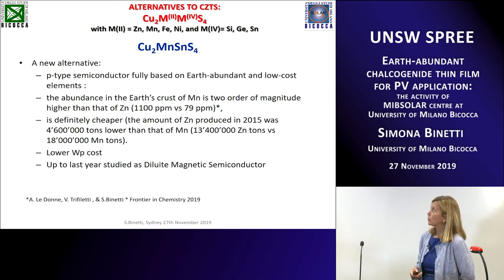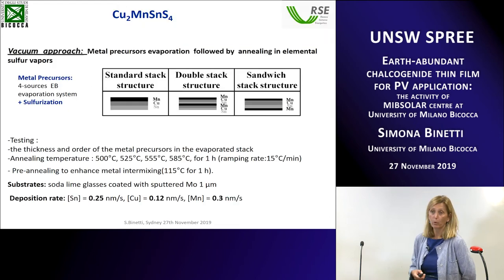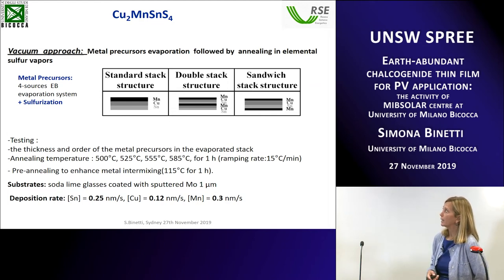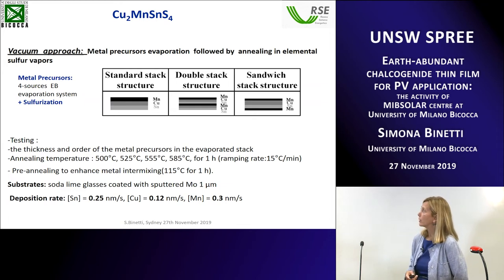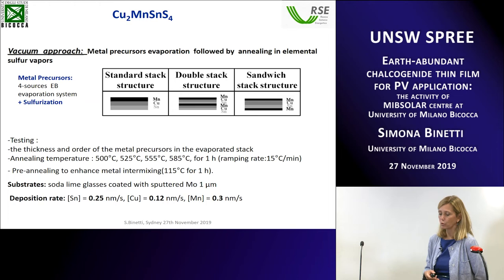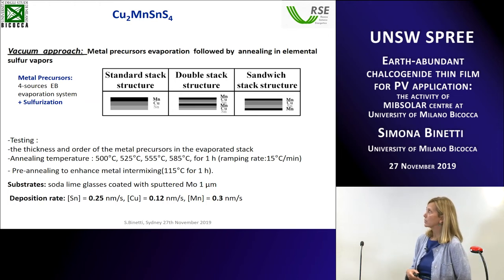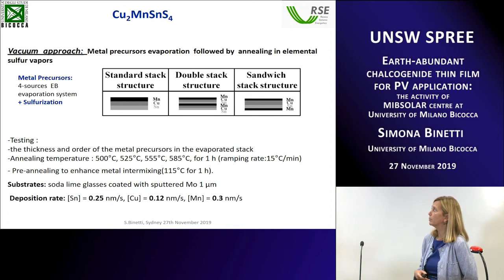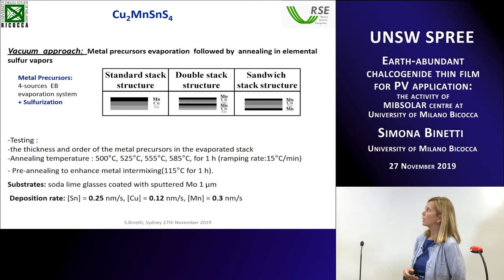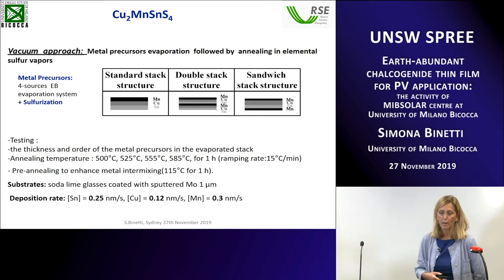This time, we started with a vacuum approach, not by sputtering. The metals were evaporated by an e-beam evaporation system, followed by an annealing in elemental sulfur vapor, standard annealing. So we studied how to change the sequence of the metal deposition by e-beam, and then at the end which stack structure was the best one. Then we studied, of course, which temperature is the best one between 500 degrees C and 585 degrees C for about 1 hour.